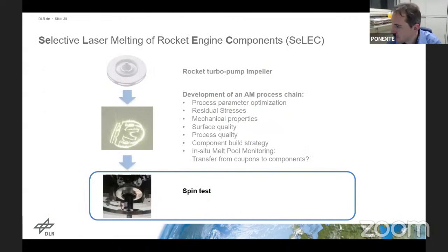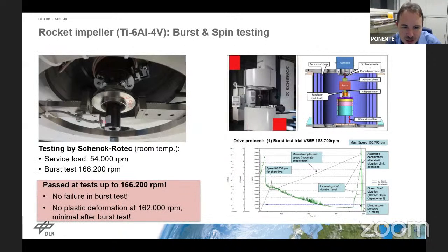So, with this, I want to finish my talk now. In our project, we were able in the end to produce this impeller, to process this impeller with heat treatments. We used a heat treatment actually in combination with hot isostatic pressing here, because this gave the best mechanical properties. And it also ensured that we didn't have, let's say, critical manufacturing defects in the parts that would in the end ruin the testing.